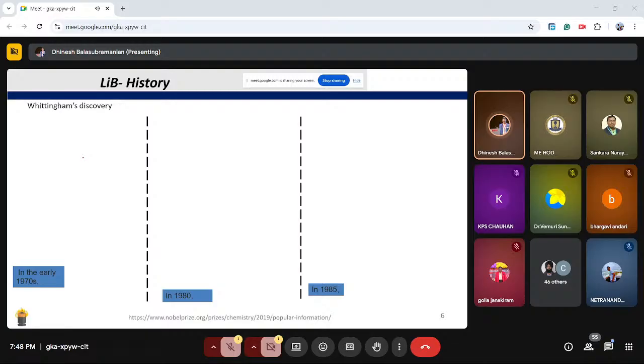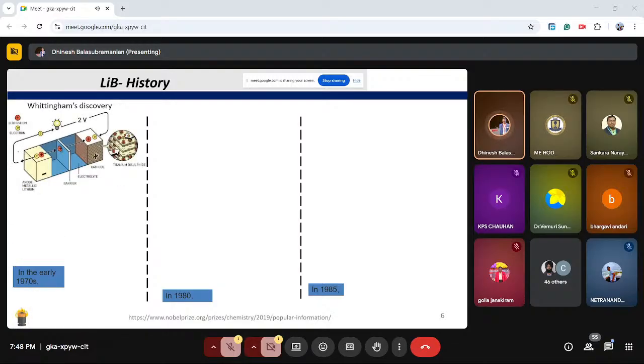So it started with the Whittingham discovery. Whittingham tried to deal with anodic metallic lithium in the initial state. As I said, lithium is highly reactive and has a higher tendency to lose an electron. If the electron is allowed to get loose from this configuration, you need to allow the electron to make a longer distance and move in the opposite direction. So in this case, he tried to deal with the cathode. In the cathode, he dealt with titanium disulfide as the primary source material.